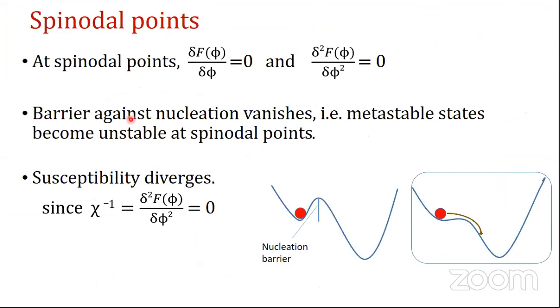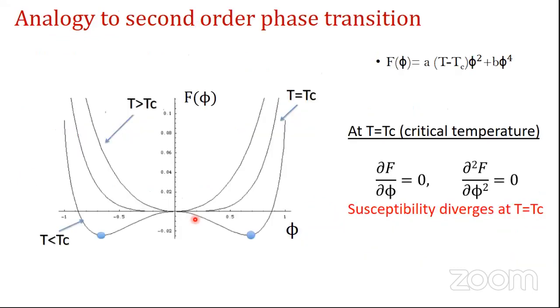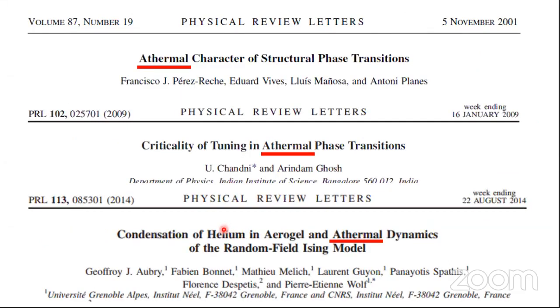So now at this spinodal point, the first derivative is always zero, and the second derivative, as this is the point of inflection, is also zero. So basically the two wells convert to a single well, and hence the susceptibility, which is the inverse of the second derivative, diverges. This is the usual case for a second order phase transition at the critical temperature. The first derivative and second derivative of the free energy vanish, and the susceptibility diverges at this critical temperature. So now we are talking about this athermal transition in a thermally driven phase transition.